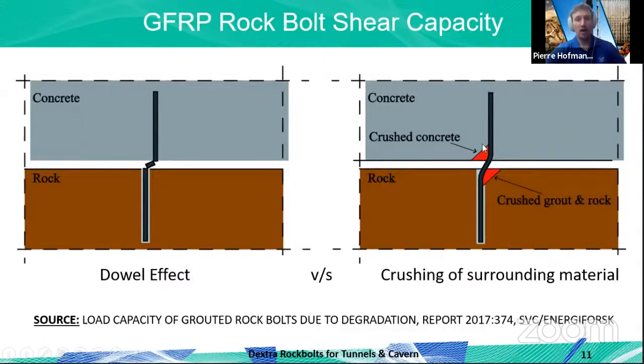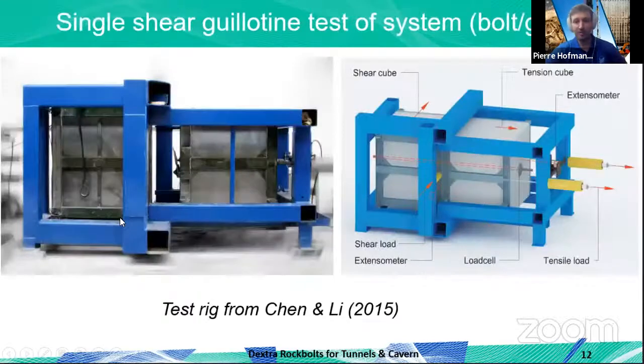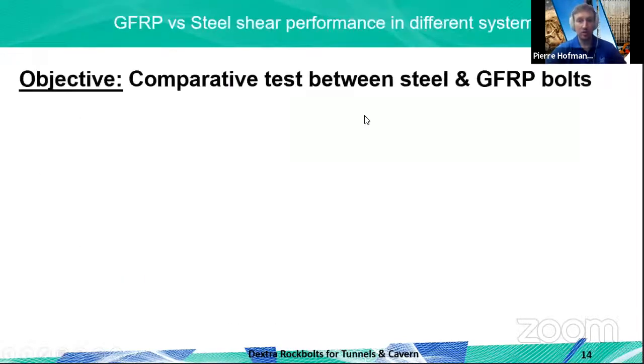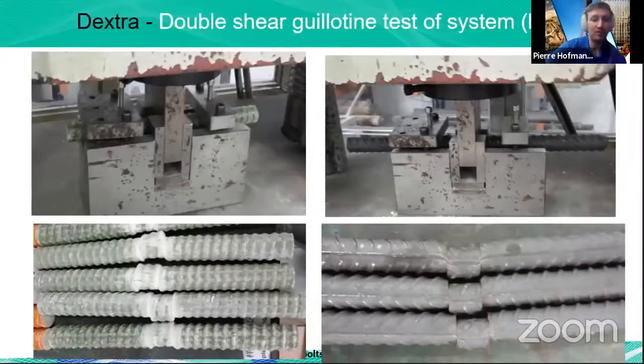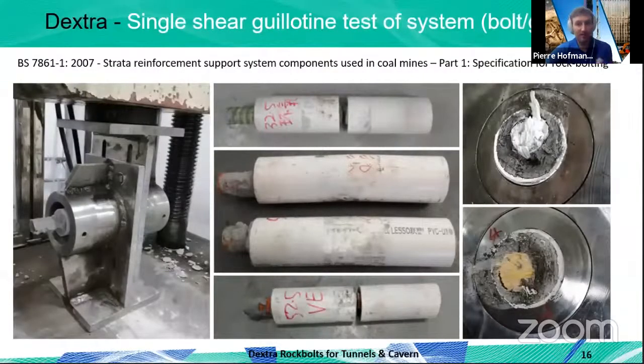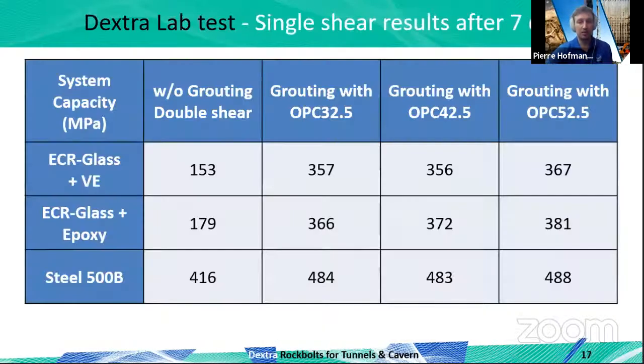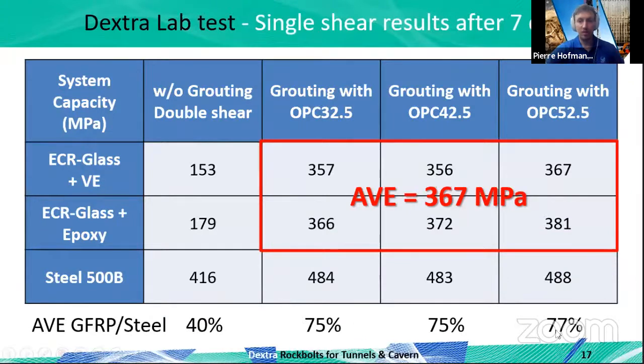And that's why the GFRP rebar will have more shear strength than what we characterize normally with a simple shear test in the lab. I'll be again very brief. There are a lot of tests that have been done. We did some also on the Dextra side, but to give you an idea, we did a comparative test. When we compare the pure shear strength of GFRP and steel side by side, GFRP only achieves 40% of a steel rebar. But when we do the same with surrounding material, with grout, and I repeat, with concrete it would be the same, I go straight to the conclusion. It doesn't matter actually the concrete grade, 30 MPa, 40, 50 MPa, GFRP, thanks to the surrounding material, is able to develop 75%.